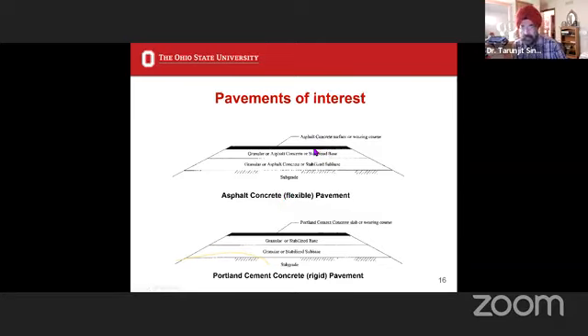So this wearing surface, what we're talking about, the pavements we are looking at essentially have failed in rutting because the base and the sub-base have failed. Water infiltration. So our objective is to stabilize these two with some sort of cementitious or pozzolanic material. For the asphalt wearing surface, there are several ways to do it. One, which is common in the US, is you essentially scrape off the entire wearing surface and take it to a hot or a cold recycling plant. Both options are there, whichever one works.